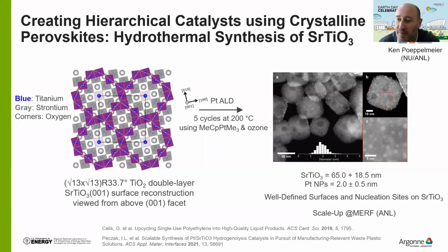That means that due to this cube-on-cube epitaxy, the platinum under very harsh conditions doesn't sinter and doesn't move on the surface. We have a very strong stabilization that in theory could be very, very important to deconstruct plastic waste at high temperature. And this is what we did.